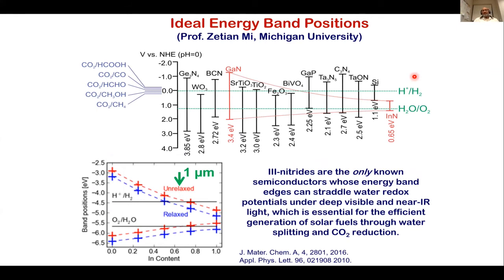So in fact, we've been looking at what the best materials are for this application. I borrowed this slide from my colleague, Professor Zetian Mi from the University of Michigan. His group has done a lot of simulations and looked at which materials are very good. One of the important requirements is that the redox potentials of water need to be within the band gap of the semiconductor. Here's a conduction band, here's a valence band edge, and you need to have this straddling the two.